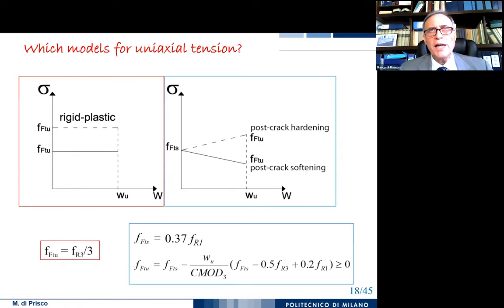So what we did, we suggested essentially two simple models. One is rigid plastic, and in the other one the post-peak behavior is linear. So it's linear, that means usually it's a linear softening, but sometimes for special materials we can arrive to have also a hardening behavior. And we correlate the values which characterize these simple models, FFTU and FFTS, with the residual flexural strengths we have identified by means of the three-point bending test I presented before.